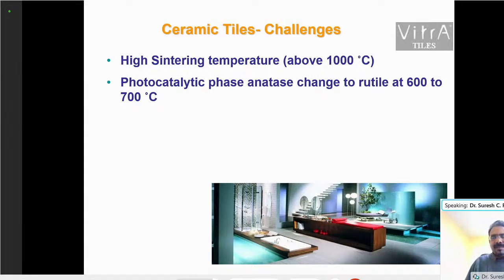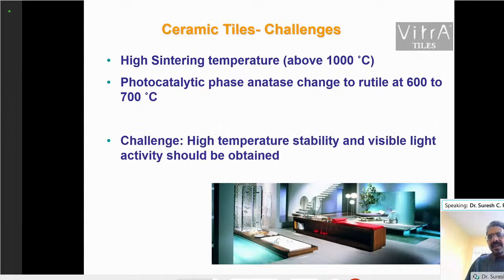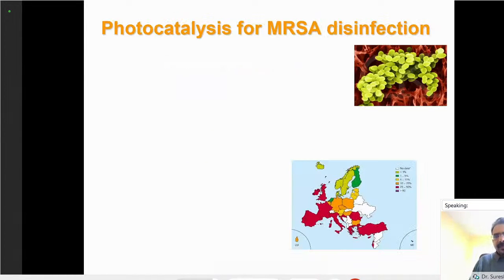But still we had the other problem, high temperature stability. Even though we developed a titanium dioxide which can work under visible light, there is one more challenge remaining. That was high temperature stability. Why? Because we discussed that the anatase form, which is the photocatalytic form, changes to a non-photocatalytic form, which is rutile, at a temperature of 600. So the processing temperature of tiles is 1000 degrees Celsius. So the next challenge was to develop a high temperature stable titanium dioxide.